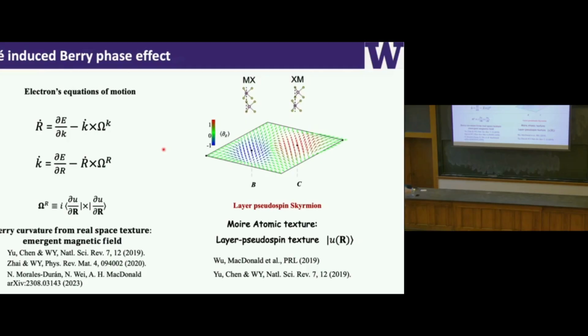The other way you can think about it is, as long as you make a moiré superlattice and you have these moiré pseudo spin skyrmions, then what it means is we don't need a magic angle to do this, because this picture already holds. So, coming to detail, you can realize such an effect in a large range of twist angles, as long as the bandwidth is small. So there's a phase space for this to happen. Okay, I'm going to emphasize this a bit more later.